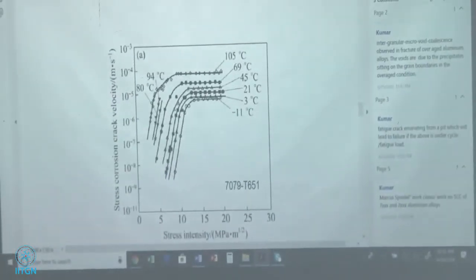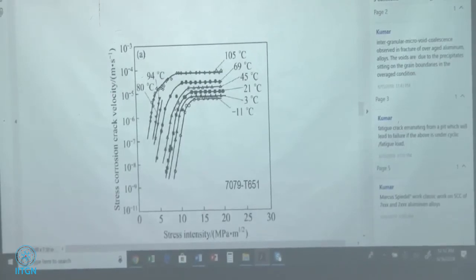But look at the effects, nice effects. Minus 11, 3, 21, 45, beautiful. But look at how fast the crack is growing. 10 to the minus 4 meters per second, multiply that by 10 to the 3, it's 0.1 millimeter per second. Right there in the top. That's 10 to the minus 4 almost, right? Times 10 to the 3, that will give you millimeters per second. That's almost 0.1 millimeters per second. The crack is running even at this low stress intensity of 5 at that temperature in this material.